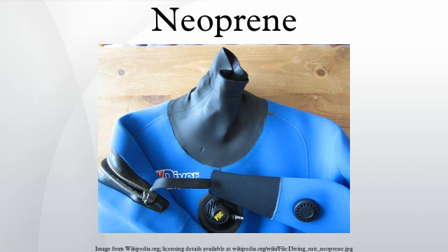A recent advance in neoprene for wetsuits is the Superflex variety, which mixes spandex into the neoprene for greater flexibility. As a result, wetsuit neoprene sheets are manufactured in different grades dependent on the application. Diving suit neoprene is denser and less flexible. This ensures its durability and reduces compression at depth. Sailing wetsuits are never exposed to large compressive forces and contain more gas, so are warmer for the same thickness.